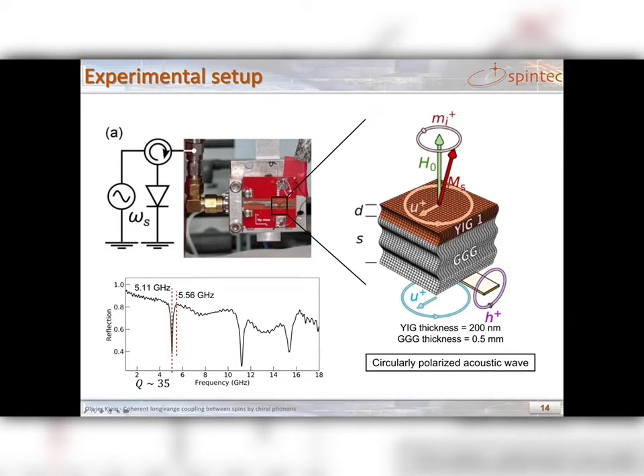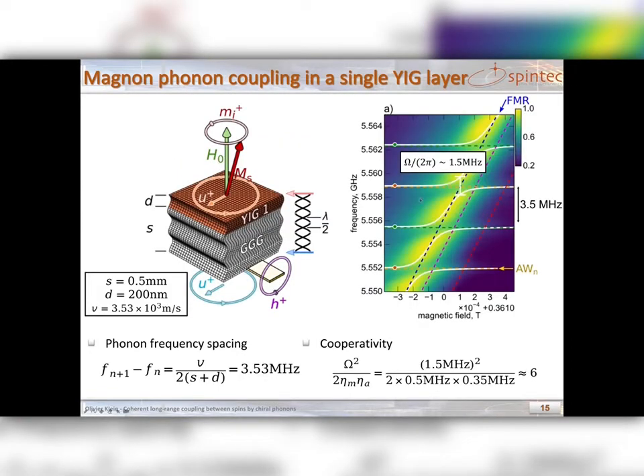A magnetic field is applied, in this case, out of plane, in the normal direction. The antenna excites the YIG layer, and due to the magnetoelastic coupling, this creates shear wave rotation of the crystal, which can be viewed as circularly polarized phonons. So in spectroscopy, we usually do field and frequency sweeps. Here is the result when we do very fine steps. The blue line represents the Kittel resonance, and the slope is the gyromagnetic ratio in this case.